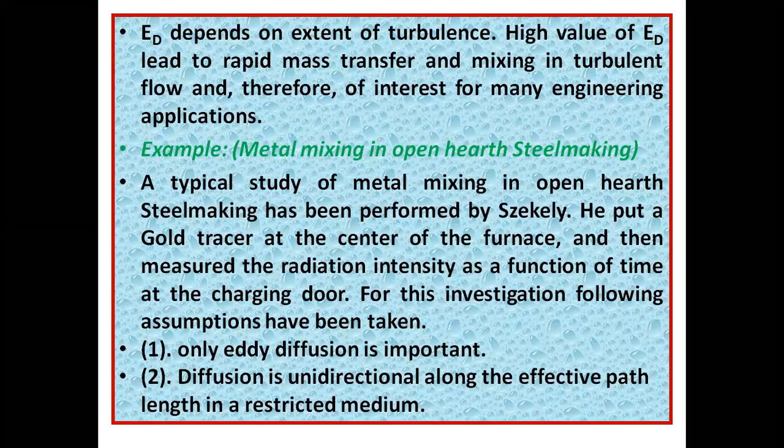A typical study of metal mixing in open hearth processes has been performed by different workers. In this particular study, a gold tracer was put at the center of the furnace and then the radiation intensity was measured as a function of time at the charging door. For this investigation, the following assumptions were taken. Assumption 1, only eddy diffusion is important. Second, diffusion is unidirectional along the effective path length in a restricted medium.